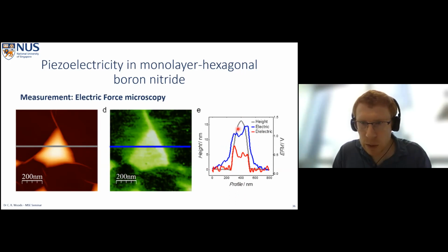But the first harmonic has some variation as we go across the top of the bubble, but it's hard in this region to decouple that signal from the topography signal. But once we leave the bubble, we find that for several hundred nanometers, we get an EFM signal propagating into our samples. And this is our piezoelectric signal. This is due to our induced charge and the strain gradient around these bubbles.